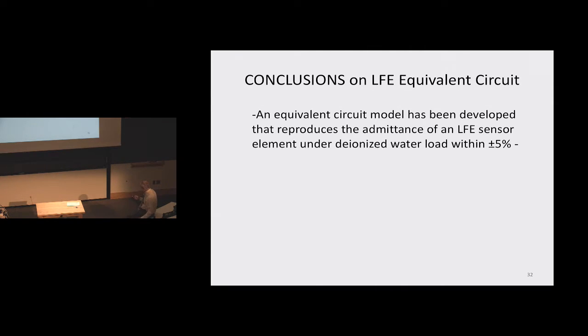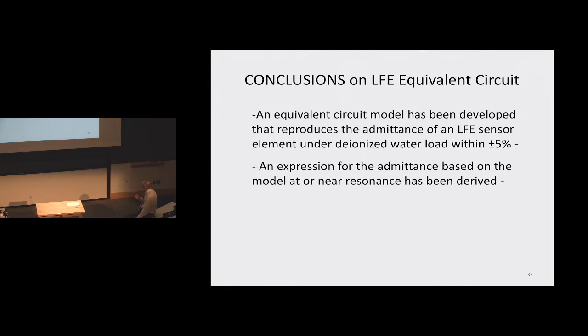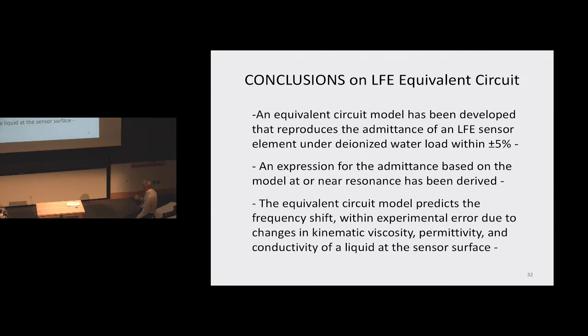All right, the conclusions. An equivalent circuit model has been developed that appears to reproduce the admittance of the LFE sensing element under deionized water loads. An expression for the admittance, based on the model at or near resonance, has been derived. The equivalent circuit predicts the frequency shift, within experimental error due to viscosity, permittivity, and conductivity changes on that surface. Okay.